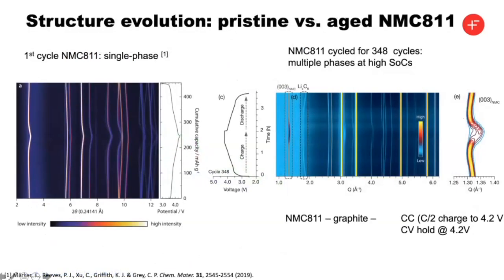So just to go back then to remind you about these structural evolutions on charging. This was the pattern I showed you initially, where you take an 811 and you charge it, and there's the expansion in the c axis and then the collapse. What we're now doing is looking at what happens to these diffraction patterns as you cycle the NMC811 for many cycles. So this is an 811 that's seen 348 cycles. So we're charging it at C/2, and then we hold it at 4.2 volts at constant voltage.